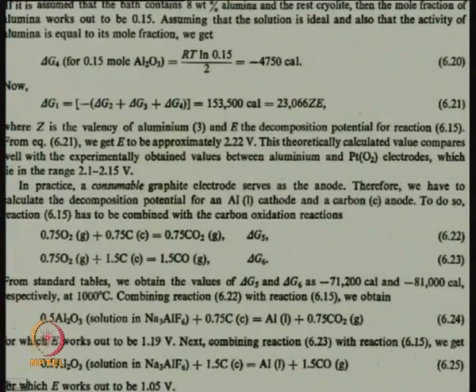That oxygen ion, when it reacts, deposits on carbon, and consumes oxygen and carbon to produce CO or CO2 depending on the temperature. And because oxygen is consumed, the decomposition reaction is aided, made simpler. Let us calculate that. In practice, a consumable graphite electrode serves as the anode. Therefore, we have to calculate the decomposition potential for an aluminum liquid cathode and a carbon, this crystalline solid anode.